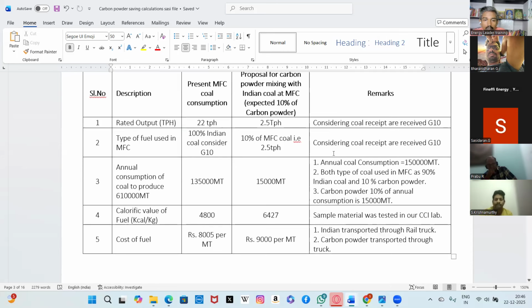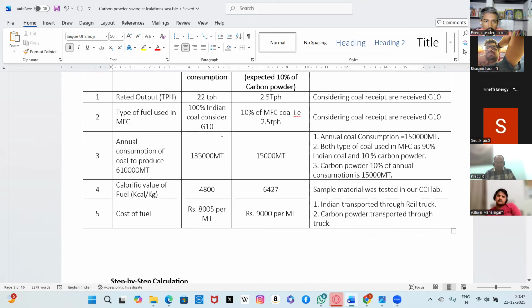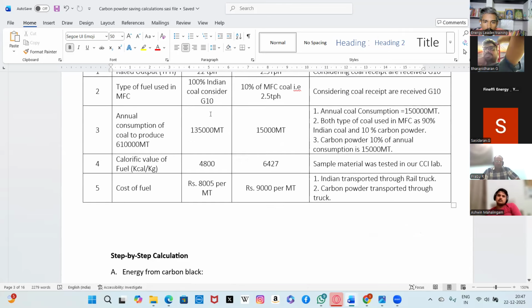This is the proposal. Our rated output for the fluidization chamber, where the coal is burnt for the calcination process, is 22 TPH. In that, only 10% I am replacing, that is 2.5 TPH. For the kiln also it's the same, both combined together 22 TPH, and I am giving 2.5 TPH as 10%. Okay. On calculating as a whole, 1,50,000, which is the yearly consumption, 135,000 as Indian coal and 15,000 metric ton as carbon powder.